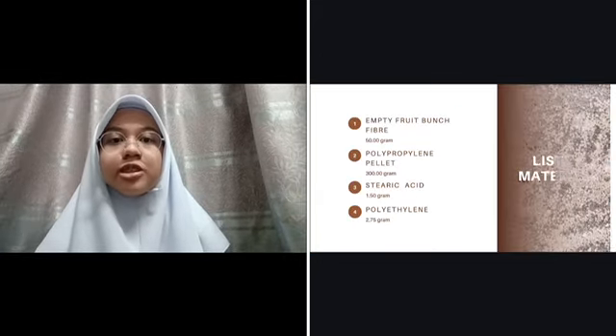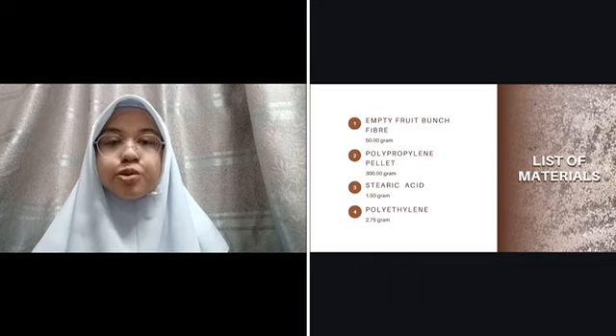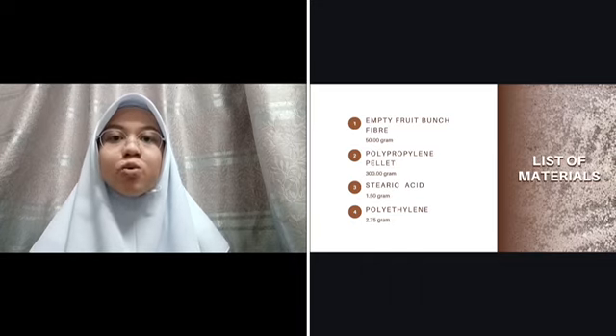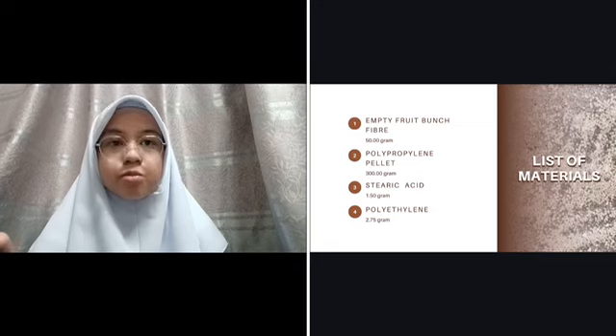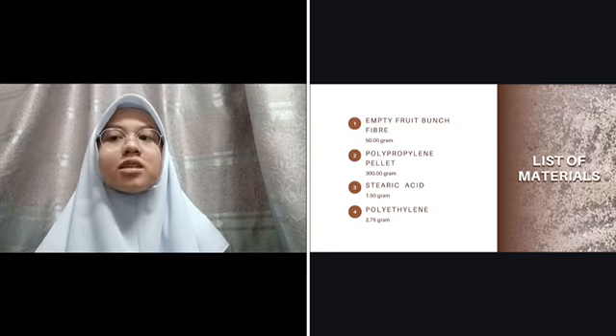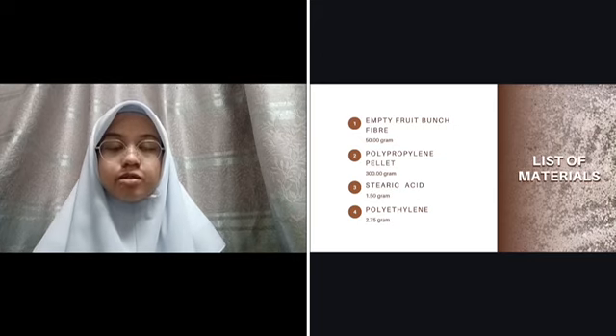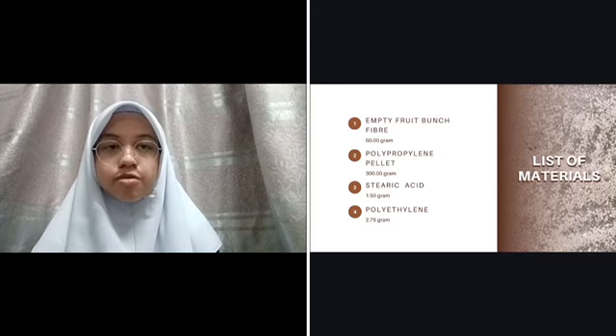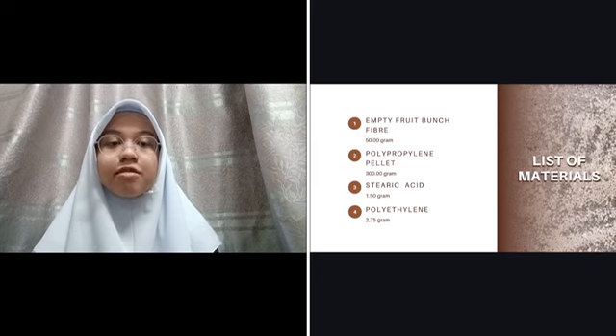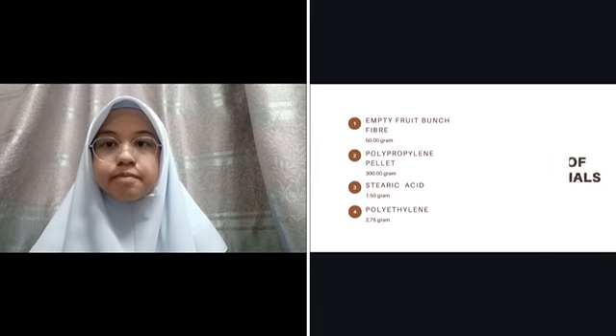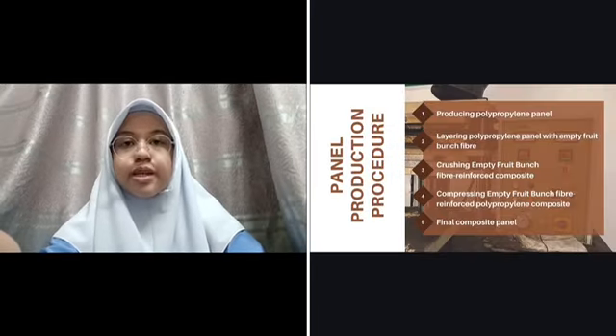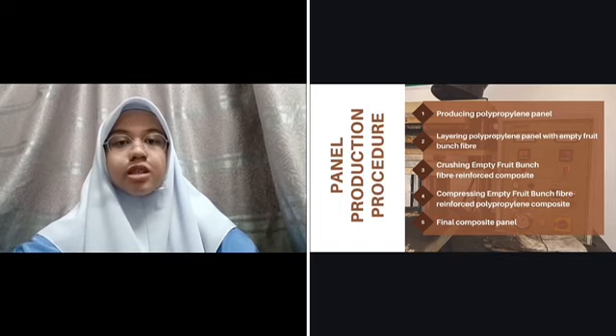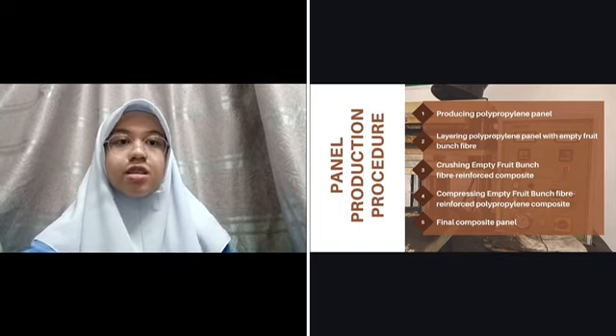So for our project, we used 4 materials to produce our composite panel, which were 50 grams of empty fruit bunch fiber, 300 grams of polypropylene pellet, 1.5 grams of stearic acid, and 2.75 grams of polyethylene. Now I will explain the procedures that were taken to produce our final composite.